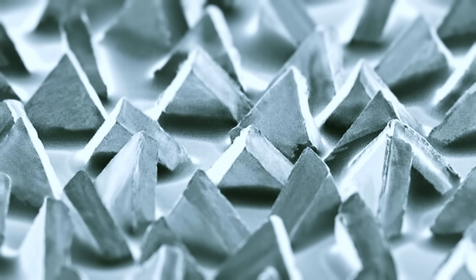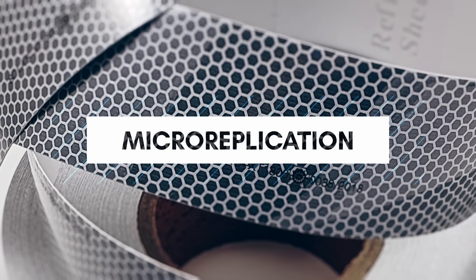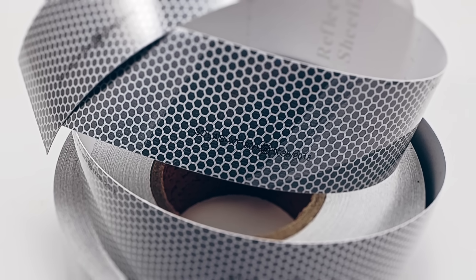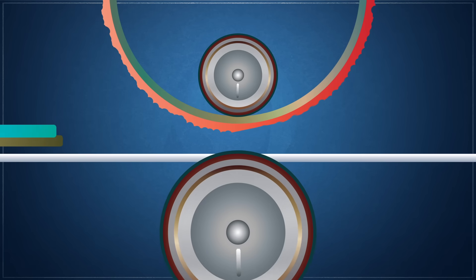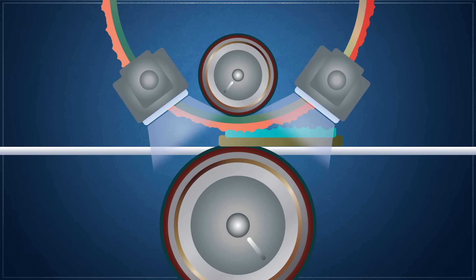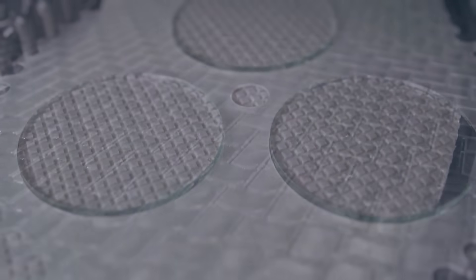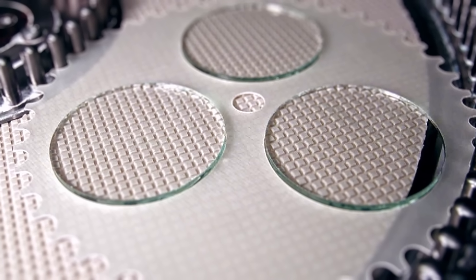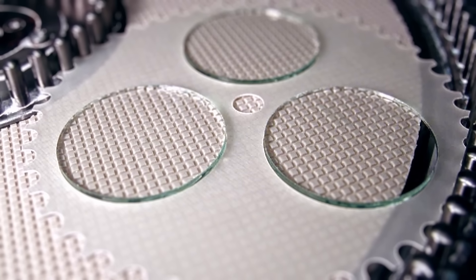While Trizact offered an improvement in metal grinding speeds, the molding process still produced a dull shape and it would take another decade of research to create truly optimally sharp mineral grains. By the turn of the century, 3M would introduce a new class of abrasives based on precision-shaped grain, or PSG, technology. PSG technology is derived from a process called micro-replication. This technique was originally used by 3M for optical applications and it was eventually adopted by the abrasive systems division as a way to produce regularized abrasive surfaces. In this process, a casting film is used to roll a microstructure onto a wet, uncured abrasive gel coating. As this occurs, a combination of UV light and heat is applied under the roller's pressure, curing the abrasive in its designed structure. Micro-replication would first be used to further refine the Trizact product line, now permitting the production of even smaller grain structures that would take the product line into the realm of high surface finishing and polishing. By 2011, the first use of micro-channel structures for debris clearing directly designed into the mineral would be introduced along with an even more elaborate grain structure specifically designed for a high-quality polishing action.